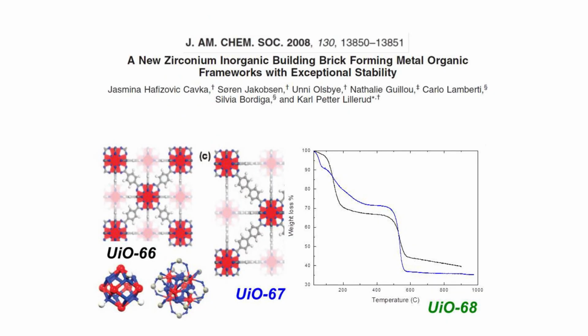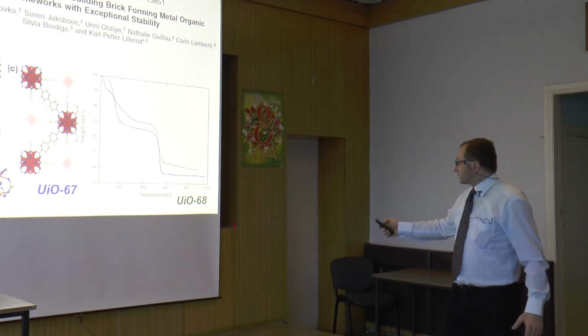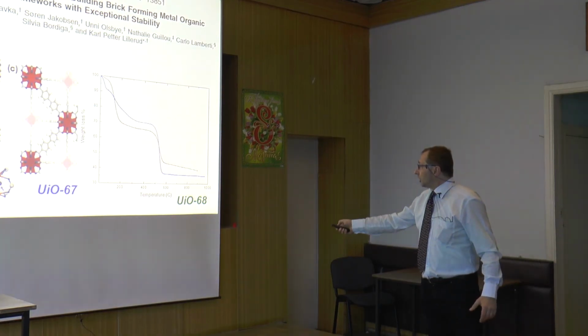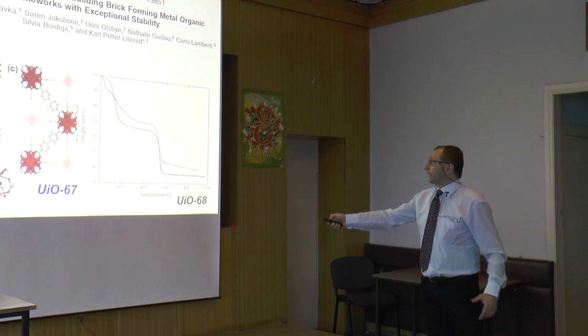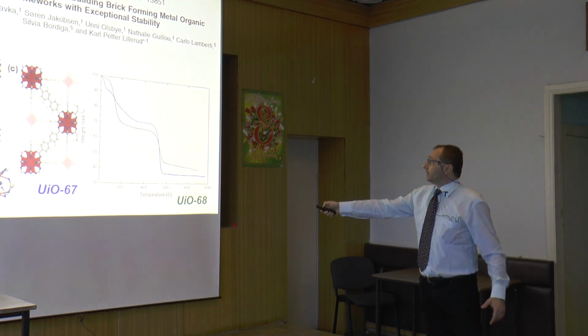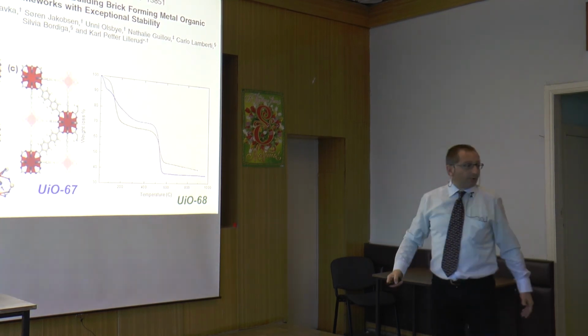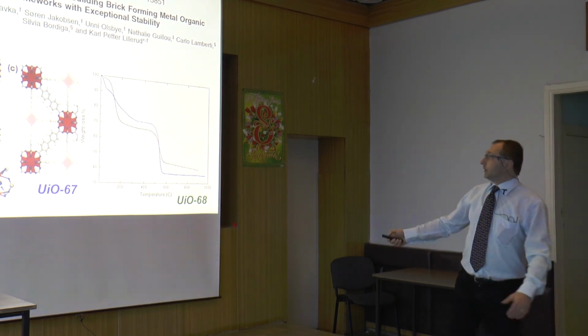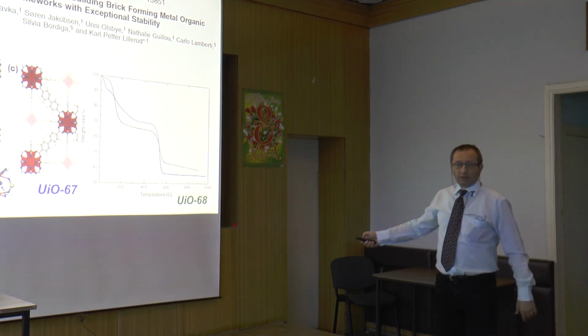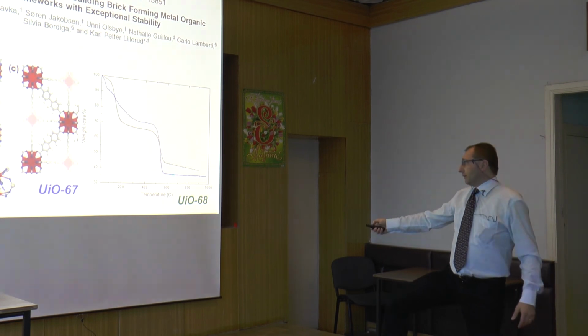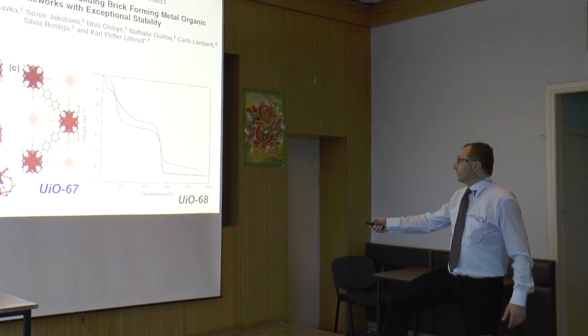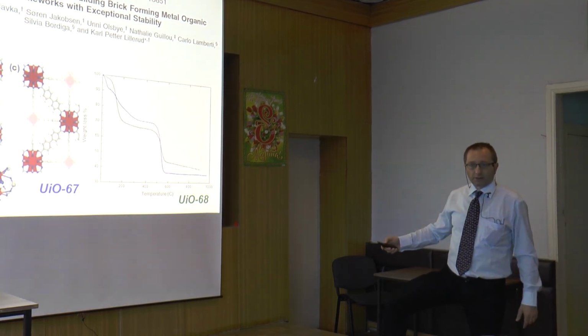And this means that you can use them for whatever application not exceeding this temperature, because this huge drop is related to the fact that you are breaking these bonds here and you are burning the organic molecules, and you end up with CO2, water, nitrogen, and so on, and you have destroyed the MOF. And here you have zirconium oxide as the remaining material.